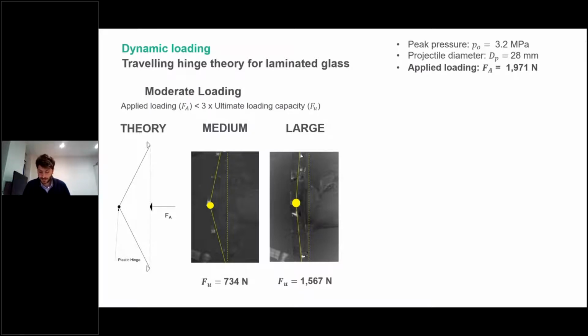The same also applies for short duration pulses with a moderate magnitude loading that is less than 3 times the static collapse mechanism. This applies for the medium and large cross-section specimens, as the applied loading, as you can see here, marked as FA on the top right, is less than 3 times the ultimate loading recorded from the previous low temperature bending tests performed.